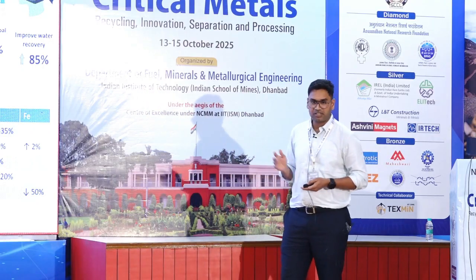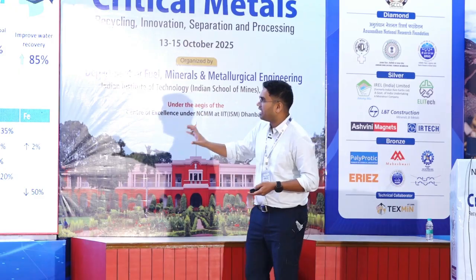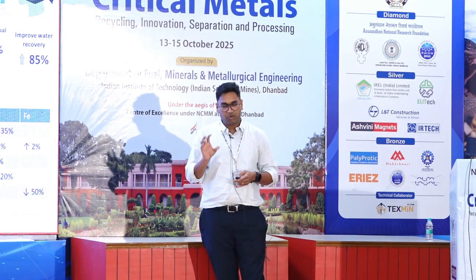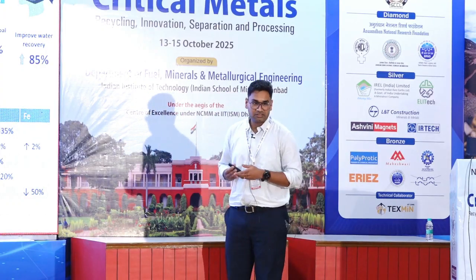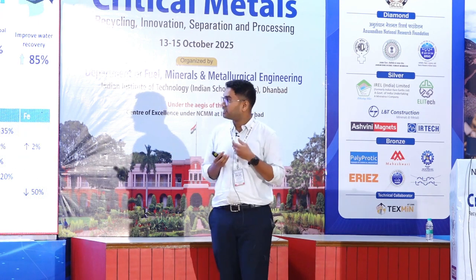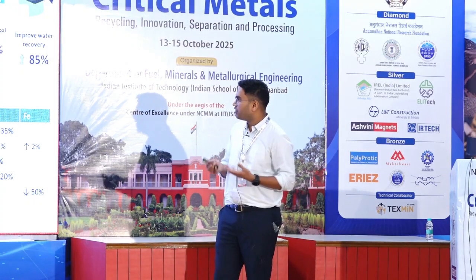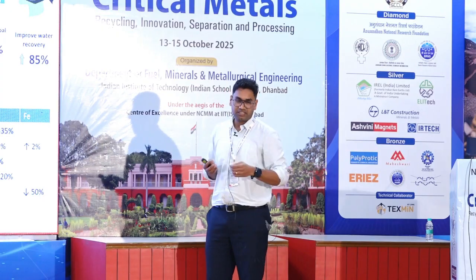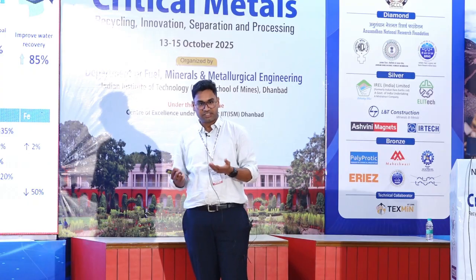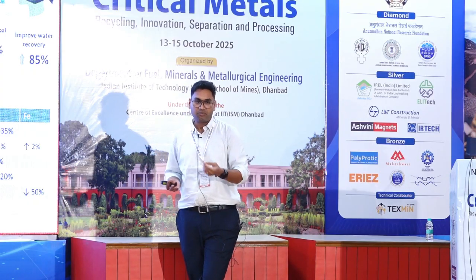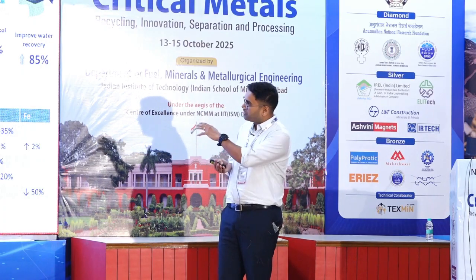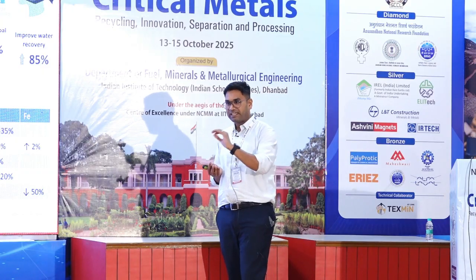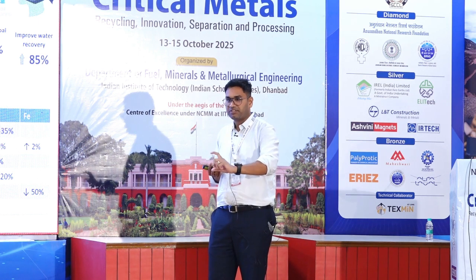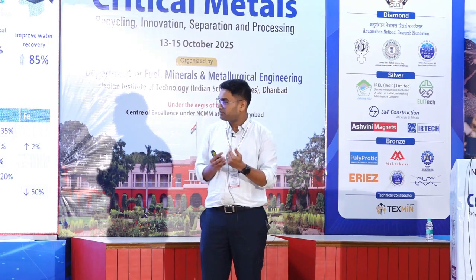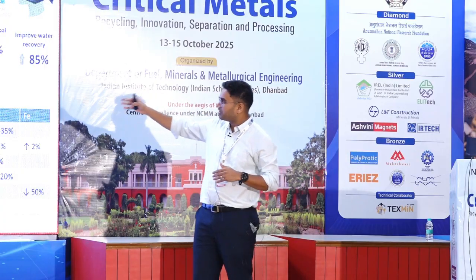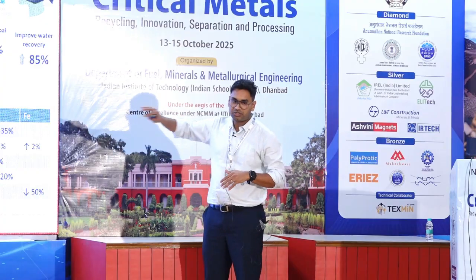The second one is a hydrofloat coarse particle flotation. This may be of less interest here, but it will help in reducing the amount of energy which is required for grinding the sample. The good part about the hydrofloat again is that it is based on the same principle as the cross flow. It works on fluidization velocities. Here, let's say we are trying to beneficiate monazite samples. Monazite is generally heavier than silica, and therefore what we do here is that we add air bubbles to the surface of monazite. By adding air bubbles to the surface of monazite, we are reducing the apparent specific gravity of monazite itself. When you reduce the apparent specific gravity, it floats out, and therefore you can concentrate the feed before it goes into the grinding circuit itself.